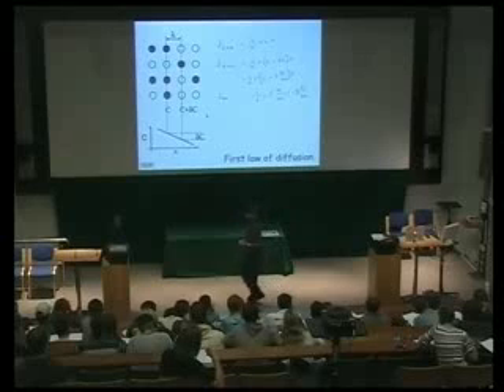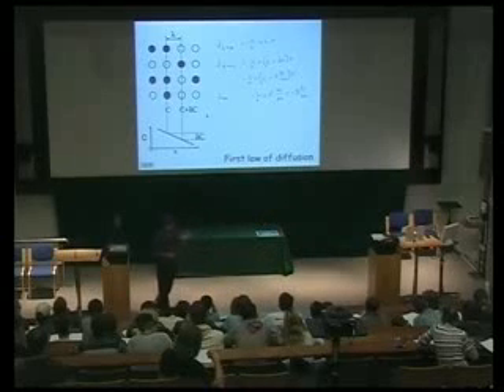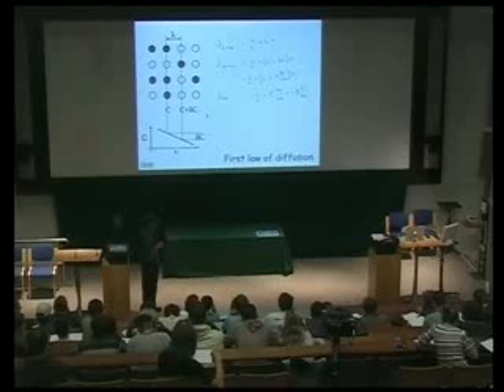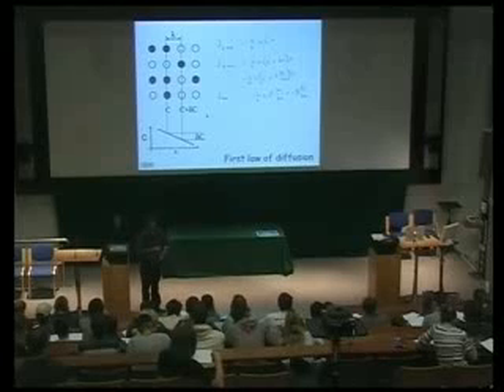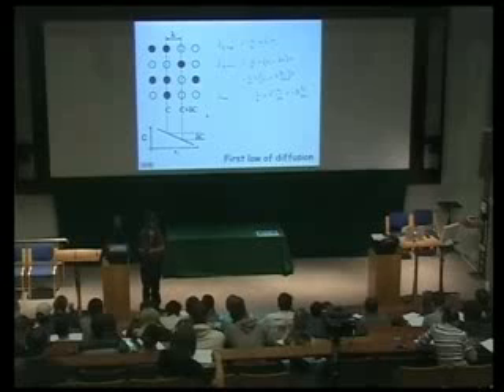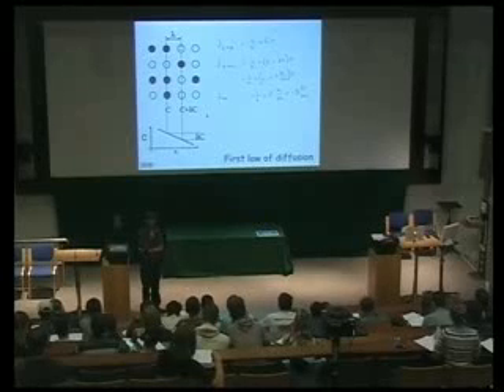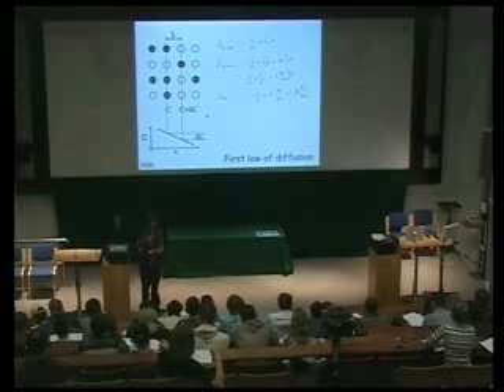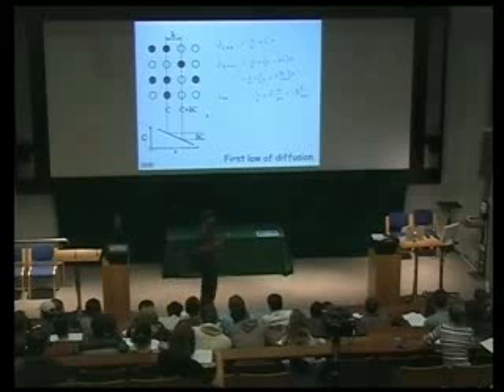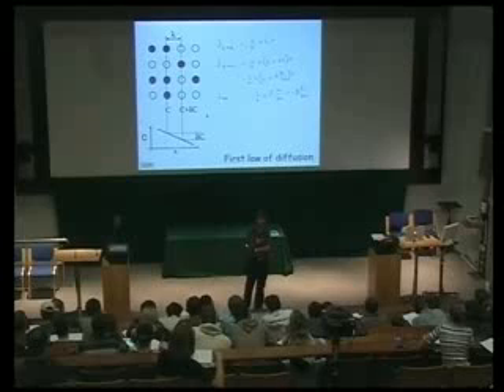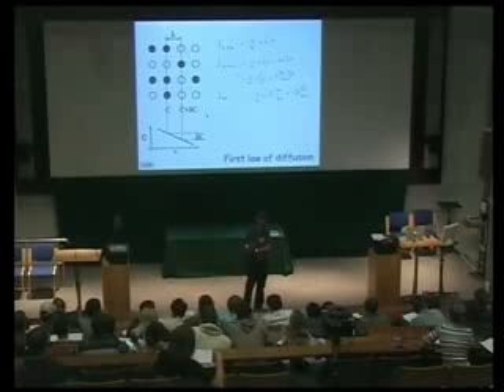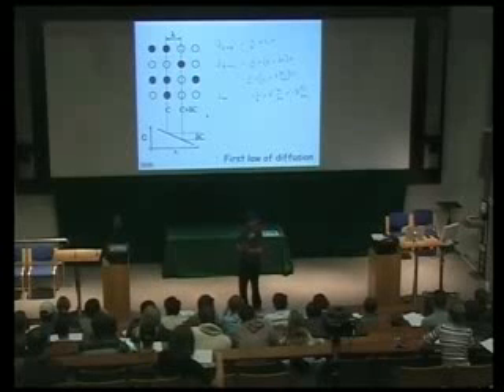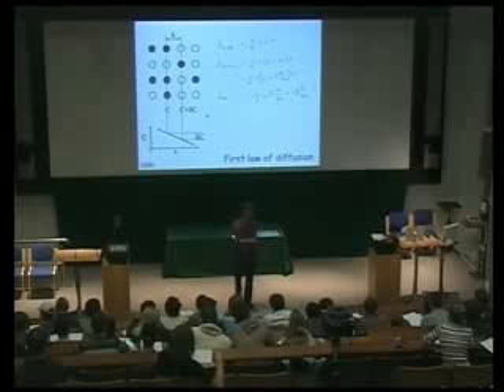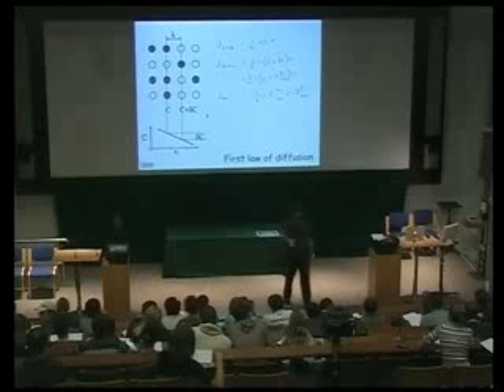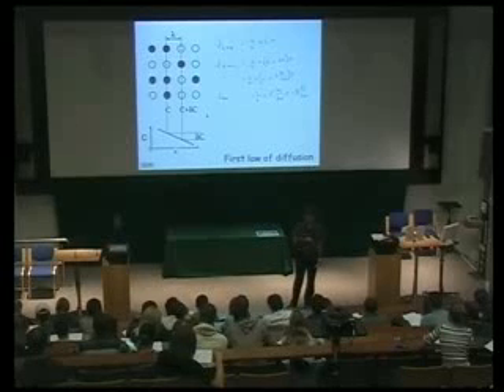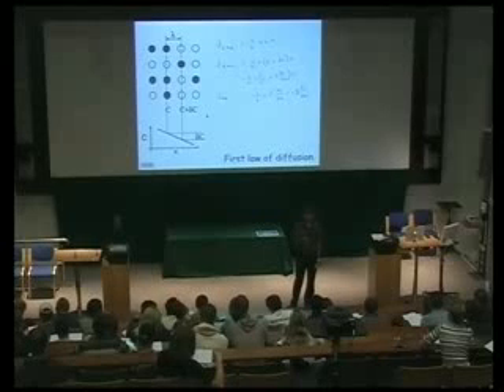Now, what is the assumption we have made in this derivation? The key assumption? Well, we have assumed that the flux is proportional to the number of solute atoms we have over here. Okay? So that's a fundamental assumption, that we are assuming that the flux will depend on the gradient of concentration. And that's a completely empirical assumption. We haven't justified it at all. It seems to make common sense, but I will give you an example in the next lecture where you will see diffusion happening up a concentration gradient. But in the vast majority of scenarios, 99% of all the cases that we deal with, diffusion will happen down a concentration gradient. But there are some very, very interesting and useful examples where it can go uphill.